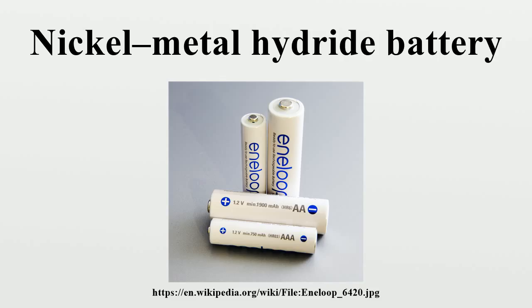Both Panasonic and Duracell suggest a maximum rate of temperature increase of 1 degree Celsius per minute. Using a temperature sensor allows an absolute temperature cutoff, which Duracell suggests at 60 degrees Celsius. With both the delta-T and the delta-V charging methods, both manufacturers recommend a further period of trickle charging to follow the initial rapid charge.